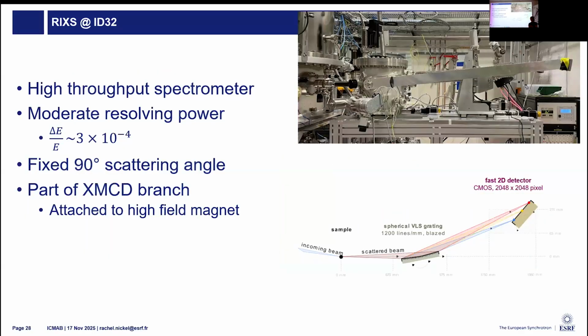We also have a smaller spectrometer. So this is our high throughput spectrometer compared to the 11-meter long scattering length. Here we only have about 2. This means that our resolving power is about 10 times less because the distance we have between our scattering grating and our detector is much smaller. So the separation we get between energies is much lower, but still reasonably good resolving power, 10 times worse than the other branch, but our flux is 10 times higher. So you can collect your spectrum much more quickly.